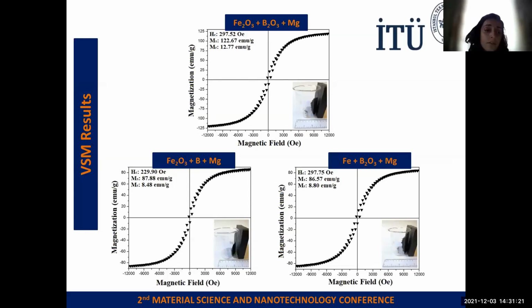And these are the VSM, vibrating sample magnetometer, results of these synthesized and purified nanoparticles. Also, you can see the magnetic hysteresis loops belonging to these three different powders, and also the image near the magnet, where the particles move toward the magnet, and it shows the magnetic properties of these materials.